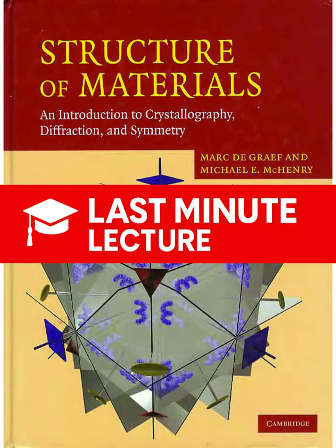It does. The vector relationship k' = k + G must hold. And because this is elastic scattering, the incident and diffracted waves have to have the same energy, so their magnitudes must be equal, |k'| = 1/λ. And the Ewald sphere guarantees that because both k and k' are radii of the same sphere. Exactly. So instead of grinding through complex trigonometry, a crystallographer can just visualize the reciprocal lattice rotating. And every time a point sweeps across the sphere, they know a reflection will occur. It converts a complex algebraic problem into a simple geometric intersection problem. It's a brilliant shortcut. Yeah.